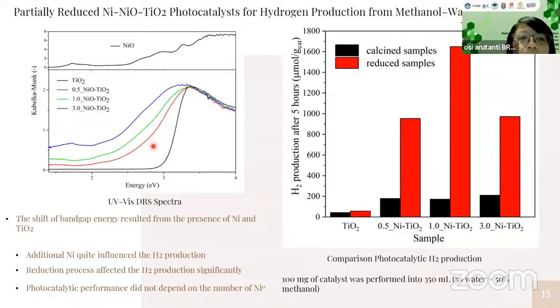This is for the UV-Vis DRS spectra. By adding NiO into the composite of TiO2 and NiO, the energy band gap also decreased a little bit. This is for the pure NiO, and this is for the pure TiO2. So we can make sure that the change of energy band gap is due to the presence of NiO and titanium dioxide.